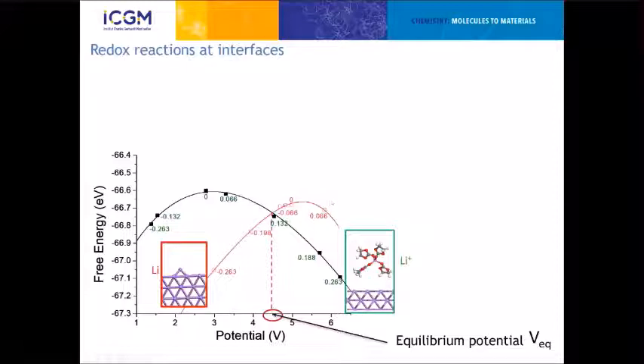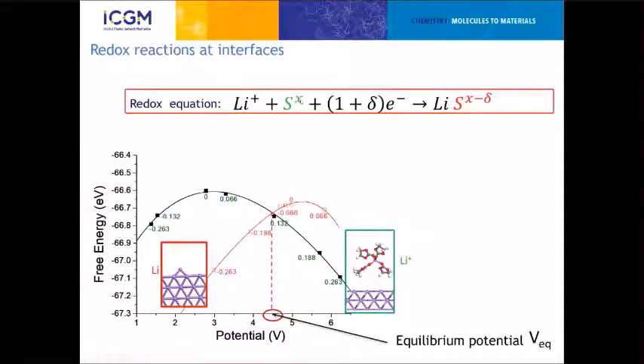When the two free energy curves cross, we get the equilibrium potential associated with the redox system. We get the redox equation, and we can even get the number of exchanged electrons. In this case, that will be close to 1. Not exactly 1, because it also includes the surface polarization that is needed to maintain the potential constant. So below this potential, the reduced lithium metal will be the stable form, and above it will be lithium plus. So by using this formalism, we are able to investigate the electrochemical reaction on the surfaces or in the double layers.